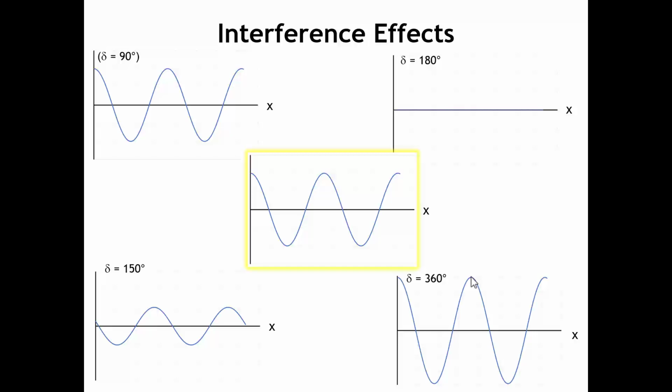Now, if you just have two X-rays interacting and they're a little bit off, or even maybe a lot off, like these images on the left here, it doesn't totally cancel each other out. But now if you were to have 1,000 or 1,000,000 X-rays that were all interfering with one another, and they're all off just a little bit, you don't have to get very far out of the fully constructive condition until you get the X-rays almost completely canceling each other. So where we see diffraction peaks in a pattern is going to be angles where we can maintain this fully constructive interference between different X-rays that are being scattered by different atoms in the crystal.